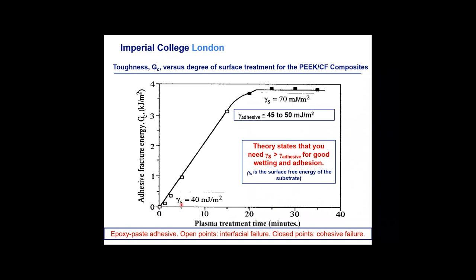Now the surface energy of the material at this stage is about 40 millijoules per meter squared. And it fails interfacially to the open points. After about 20 minutes, the surface energy is now 70 millijoules per meter squared due to the presence of these polar groups. We've increased the surface energy, and wetting theory tells us that to get good wetting and hence good intrinsic adhesion, the surface energy of the substrate, gamma S, should be greater than that of the adhesive. Now the adhesive is about 45 to 50.